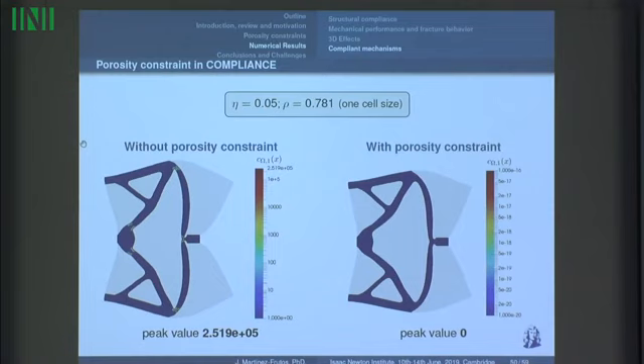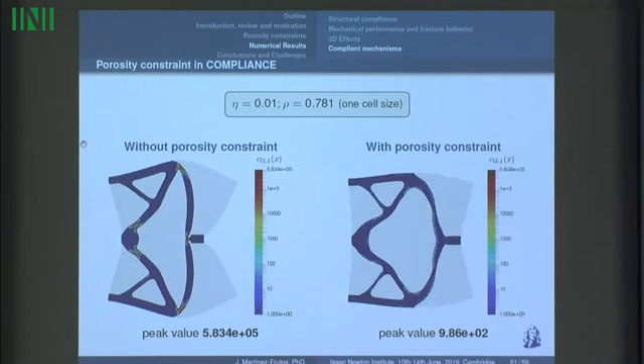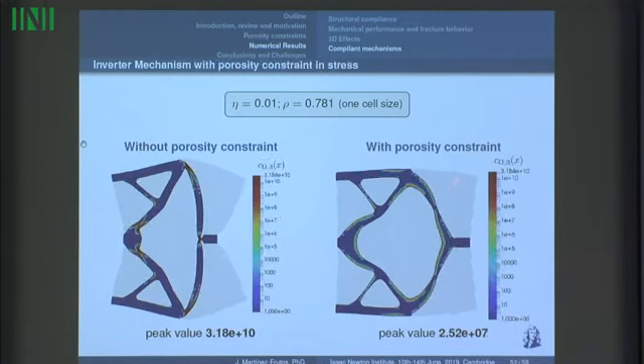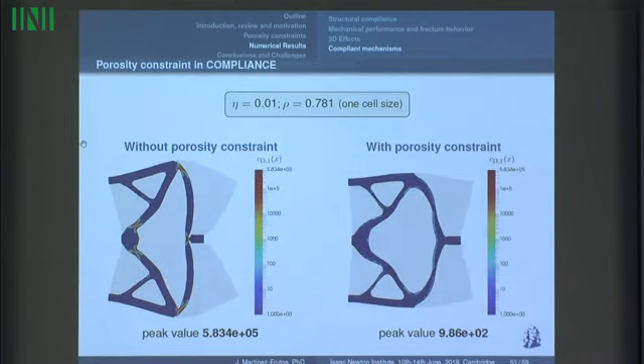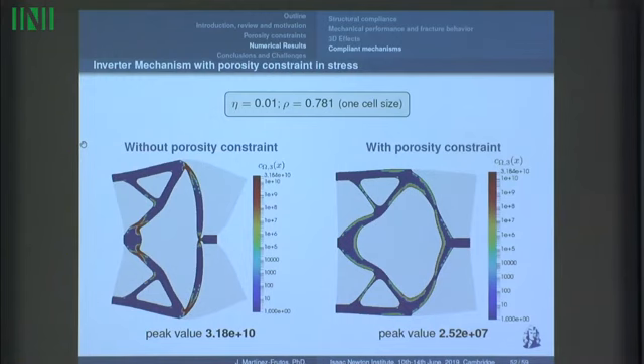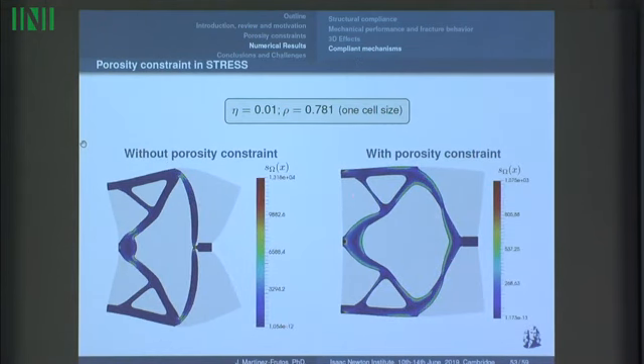So if we take here a greater value, we can be closer to the mechanism and less close to the structure. So if we decrease this value, we will have something like this, which is closer to a structure than a mechanism. So the effect is that this part increases in thickness a lot. Well, in the case of stress, we have similar conclusions to those I presented before, and we have this design that is quite similar. If you see, this is quite similar to this other one for compliance, and also has a reduction in the stress level of the structure that is reduced 1 order of magnitude in this case.